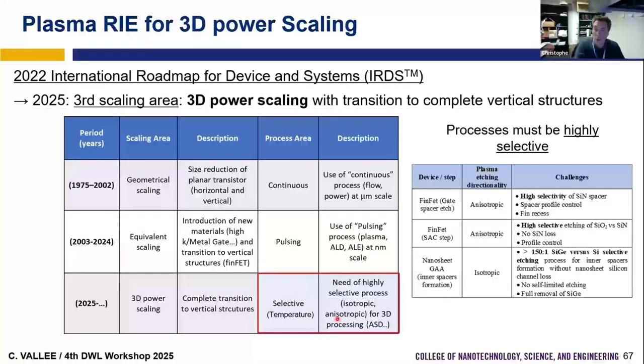So for the 3D power scaling area, all is 3D, and what is important is that we need highly selective process, but not only anisotropic etching. Now we know we need also to develop a lot of isotropic etching. So we will need to develop also plasma etching that will not be RIE, because the ionic assistance is for anisotropic. So it means that at the same time as we need to improve the RIE process, because we have high aspect ratio, high selectivity, we need to find a way to improve. At the same time, we need to maybe go away from the RIE process to go back to some spontaneous etching, radical etching process, because we need isotropic etching like for nanosheet.